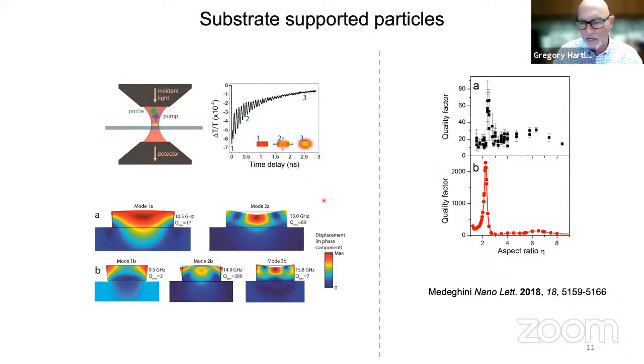So for some aspect ratios here, the modes that you're interrogating in the experiment are sort of just stuck up on the top surface of the structure, and they're not coupling very efficiently to the substrate. So you've managed to reduce the amount of radiation damping for these modes just by controlling their shape. And so in that case, you can get structures that have very large quality factors, right? 70 to 80, which really starts to become quite large.